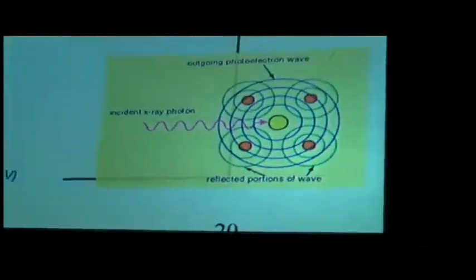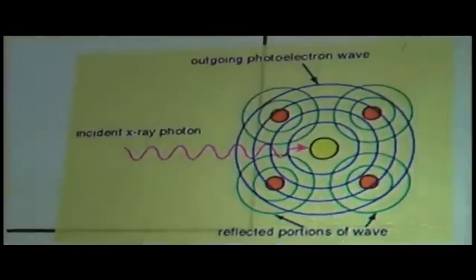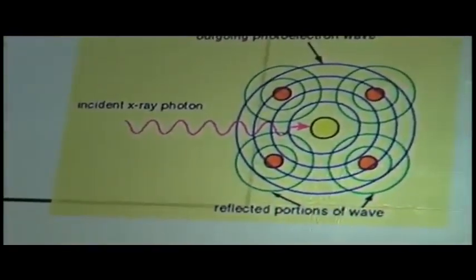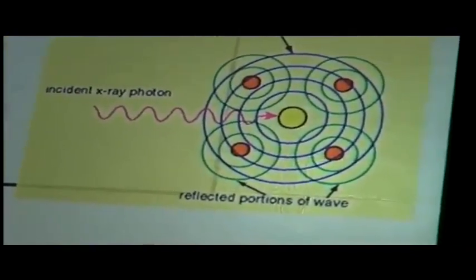I don't try to assume that everybody knows about XAS, which is a combination of XANES and XAFS here, so let me give you a quick tutorial in this. Basically, when we hit a central atom with a high-energy X-ray, we kick out a photoelectron that can interact with the neighboring atoms to tell us many things about what's going on in the surface of the catalyst. The far left portion of the spectrum is called the XANES, and that tells us a lot about the type of the central atom, the amount that's there, and the oxidation state.